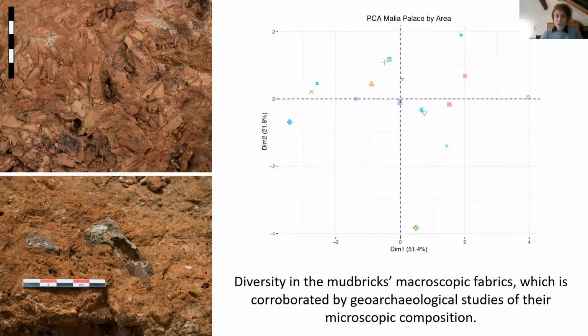As we said earlier while describing the macroscopic composition of the mudbricks, there are strong dissimilarities between mudbricks with a homogeneous or fine macrofabric and those with a significantly coarser and heterogeneous macrofabric. And this macroscopic diversity is confirmed by the variations in the mudbricks' microscopic composition as seen through geoarchaeological analyses. This indeed corroborates the clustering based on macroscopic observations by showing geochemical and petrographic coherence within architectural units and small variations between separate groups of walls. So as far as geoarchaeological analyses are concerned, there is limited variability in raw materials. This is the local resource exploitation Marta has been insisting upon, but there are differences between wall clusters that are significant enough for corroborating the segmentation of the Neopalatial building project, highlighted by the macroscopic study of the mudbricks.